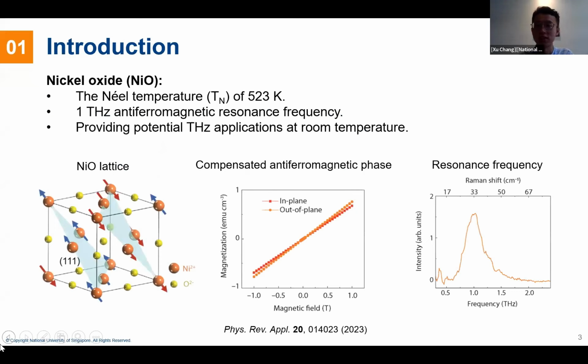Nickel oxide is a widely known antiferromagnet, and the Néel temperature of nickel oxide is around 523 K. Nickel oxide has an in-plane ferromagnetic coupling, and between planes they are antiferromagnetically coupled. From our VSM measurement, we can see it shows a compensated antiferromagnet phase.